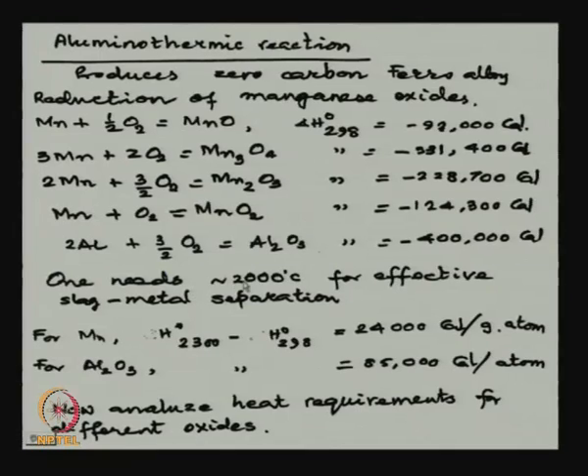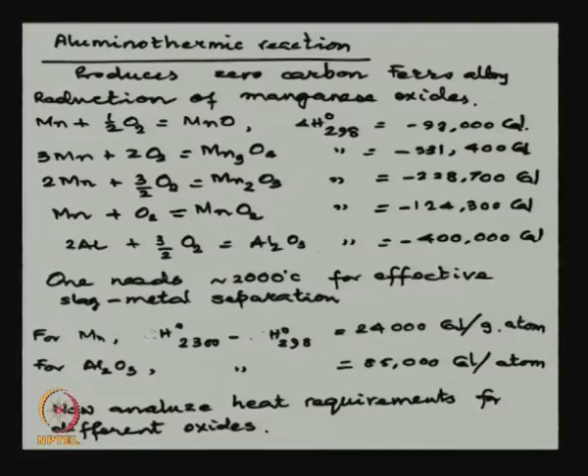Now, one needs around 2000 degrees for efficient slag-metal separation. We have to find how much heat we need for clear separation between metal and slag. We have to heat the manganese metal from room temperature to 2000 degrees. For that, the data is this much, you can get it from the specific heat, melting points and the enthalpy of melting. For Al2O3, the heat required to heat from room temperature is this. Basically, what we are saying is we assume the reaction is taking place at this temperature, then we are taking the products to high temperature. So, we need extra heat supply, so that we get a clear separation between metal and slag. Now, we will analyze the heat requirements for different oxides.